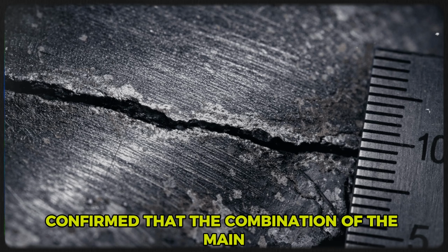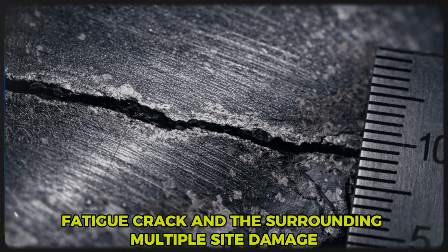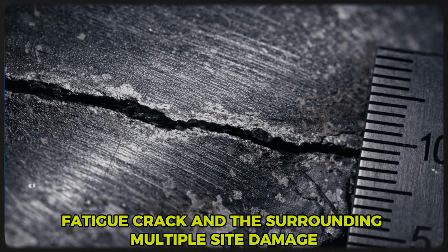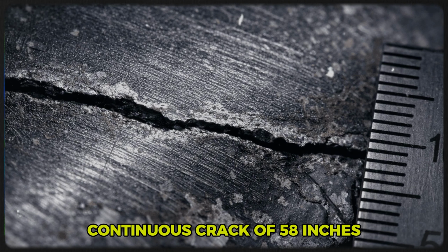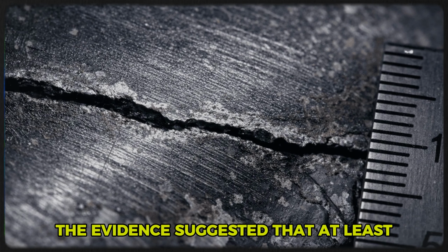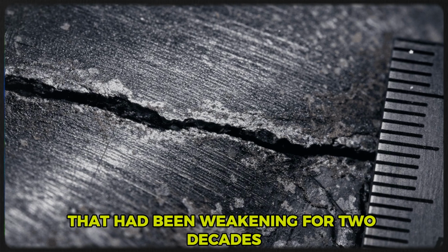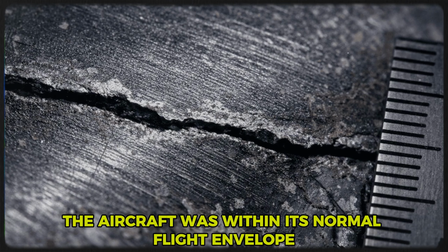Residual strength analysis confirmed that the combination of the main fatigue crack and the surrounding multiple site damage was of sufficient magnitude to produce a continuous crack capable of compromising the fuselage under normal operational loads. The threshold for structural failure was a continuous crack of 58 inches. The evidence suggested that at least 71 inches of continuous cracking was present before the breakup. The structure failed not because it was subjected to extraordinary loads, but because ordinary loads exceeded the residual capacity of a fuselage that had been weakening for 2 decades. The aircraft was within its normal flight envelope.